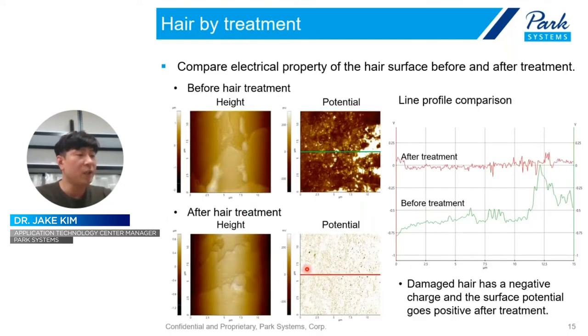And next we compare the electrical property of hair surface before and after hair treatment. Of course, once again, from the height image, there is no difference, just the hair AFM height image, but the KPFM image, like a potential image, shows the difference between before and after. The damaged hair has negative charge, and this surface potential goes positive after this treatment. So like this, we can see this surface potential or electrical property from the EFM and KPFM.